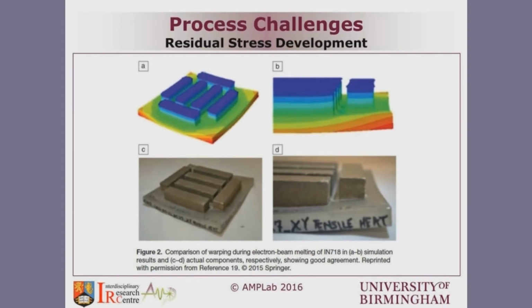But what you can see is the substrate where the component was being built, in figures D and C, shows the amount of distortion the component has experienced. That's significant—a significant deviation of tolerances and of the required performance of the parts—and in most cases that will require a post-processing treatment to control the residual stresses.